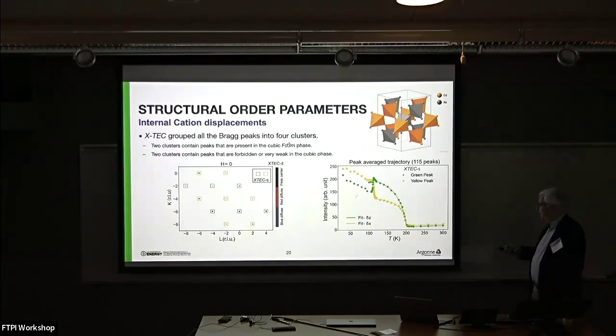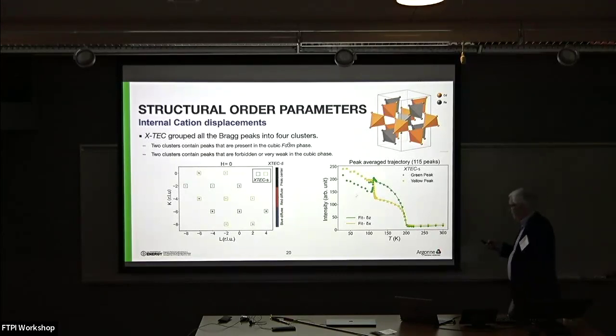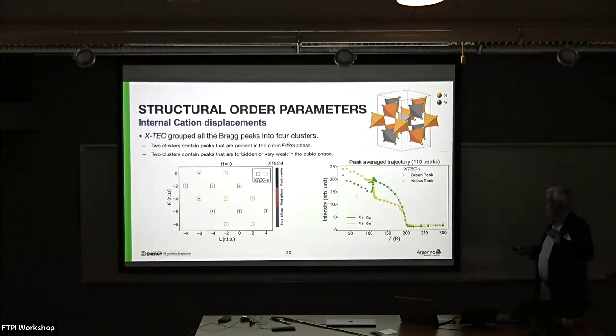But there are some, for instance, with the lower first order transition at 115 Kelvin. There are some peaks which suddenly plummet, others which suddenly shoot up, and there are other systematics with those peaks which I'll show in a second. It turns out that knowing where these Q vectors are, we could get an analytic function for the intensities, and so we know how these intensities vary according to the cadmium and rhenium ion distortions. And it turns out that there are actually positive and negative, antiphase cadmium and rhenium distortions in this material, which is causing this divergent temperature dependence in the two.